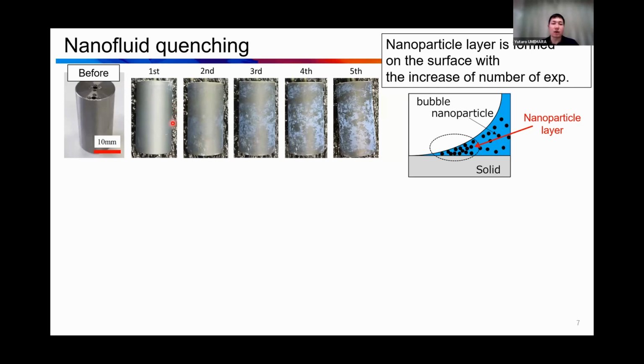So the nanoparticle layer is deposited on the surface. During the boiling case, the nanoparticles are dispersed in the liquid, and during the cooling case, a bubble comes out from the solid, and the nanoparticles aggregate in the very thin liquid film layer, and then the nanoparticle layer is formed. When we repeated the test, the nanoparticle layer is formed like this.